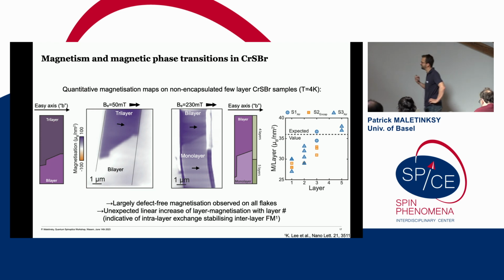And this revealed the first surprise, and something we can currently not quantitatively explain, and I'd be very happy for input, namely that the magnetization per layer seems to scale approximately linearly, essentially, initially, and then saturates only after roughly 5 layers to the expected value of a fully saturated chromium sulfur bromide flake that we can, of course, estimate from theory. So this suggests, of course, that the interlayer exchange coupling plays an important role for stabilizing the interlayer ferromagnetic ordering, but how exactly that works, again, we don't currently understand.